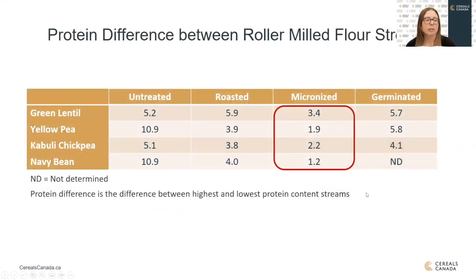So this slide is looking at the protein difference between each of the roller milled flour streams. Recall that in the previous activity, I showed that the protein contents of each individual flour stream range. So this is showing the difference from the highest protein content stream to the lowest. For example, for untreated yellow pea, there was a difference of 10.9% protein from the highest protein stream to the lowest. But when we go to some of the other treatments like micronization, the difference diminished. There was only a difference of 1.9% protein between the highest and lowest protein content streams, and this was true for all of the pulse types. You'll also see some changes in the roasted and germinated treatments, but less so. Micronization really changed the protein distribution.